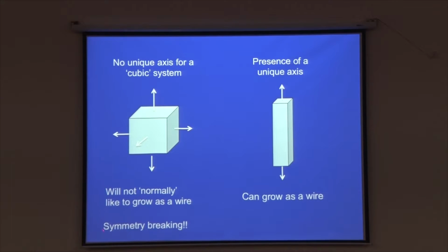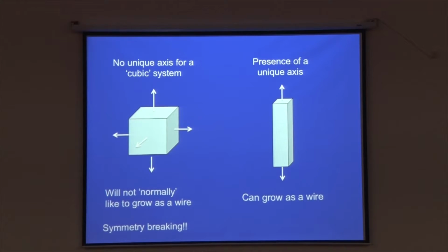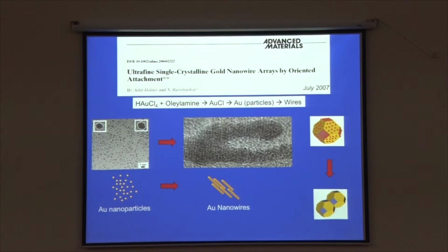There has to be some kind of symmetry breaking, which basically decides that one direction has to grow at the expense of all these symmetry equivalent directions. So, what is the mechanism for this symmetry breaking? Okay. So, we came up with this method. By the way, we were the first group to grow such thin wires without a template. This was published quite some time back, in 2007. The basic mechanism is as follows.